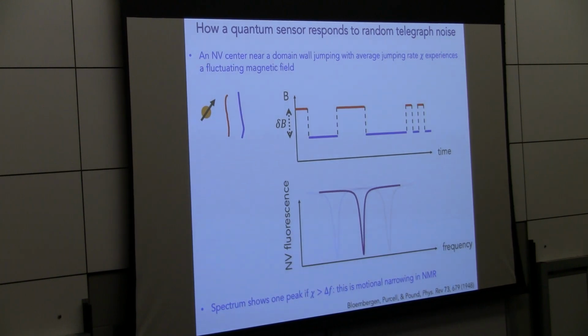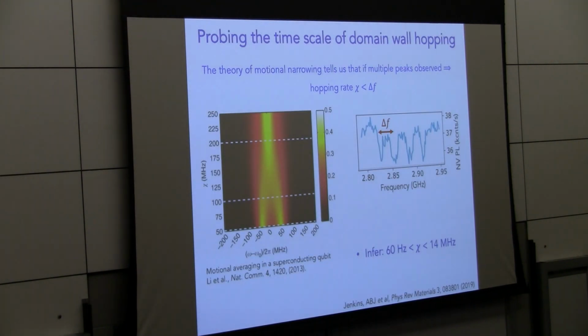This is exactly the effect of motional narrowing in NMR, which has been known, as most things in the NV community are discovered, for over 50 years in the NMR community by these prominent people. So the fact that we're seeing the two dips in the ESR spectrum allows us to put an upper limit on the rate at which the domain wall is hopping back and forth of about 14 megahertz. And again, this is about 60 hertz, the lower end of the time scale of how quickly we can actually measure. Just to say that this type of motional narrowing in a qubit sensor has been seen before in a superconducting qubit in this experiment here.